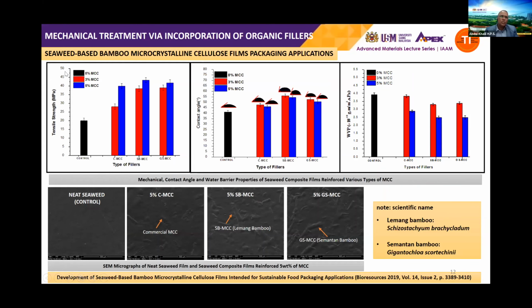Next, also through improvement using mechanical treatment, but with the incorporation of microcrystalline cellulose, MCC, organic filler. The organic filler used in the study were generated from our local type of bamboo, namely lemang bamboo and semantan bamboo. From the graph, there are significant enhancement on the tensile strength and contact angles and water permeability for the sample incorporated with MCC from lemang bamboo. The SEM micrograph shows well-embedded MCC in the seaweed matrix, indicating good interfacial adhesion between both materials. This finding also has been published in Bioresource Journal in 2019.